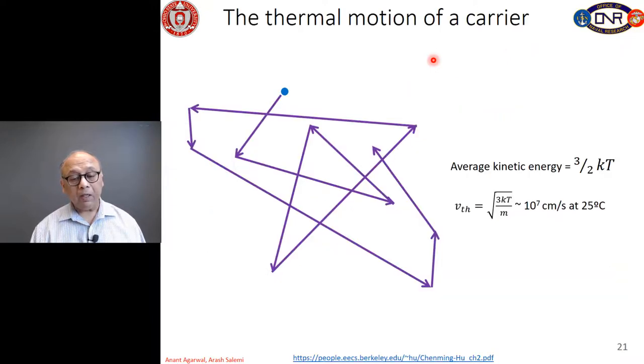So if you look at the material, and if we could track an electron, we will see that the electrons are on average moving randomly, and then they collide with the host lattice atoms, in this case, let us say silicon atoms, which are periodically placed in a cubic lattice. When the electrons in the conduction band, which are free to move around in the crystal lattice, strike or are scattered by a lattice atom, they completely come to a stop and then start moving again. So the motion of the electrons between the interstitial spaces of the silicon lattice is completely random.